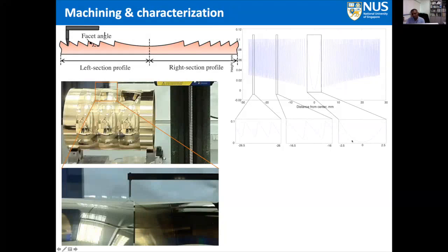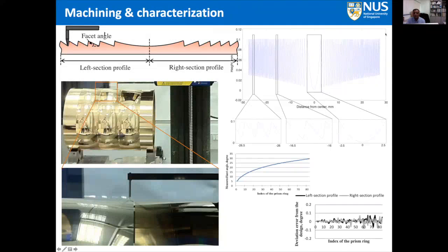However, this is not a very good way to do it because scratches will be observed, but for a study purpose, we did it. So it is just for our investigation only. So you see that the deviation of the error from the designed profile is shown at the bottom, where the left section and the right section do not deviate too much from 0. If at all it deviates, it's much less than 0.1 degree. Okay, so which is very much within the acceptable limits.